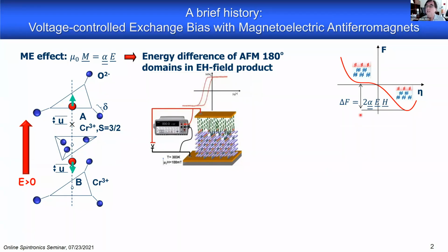Another important point I have not much time to talk about, but it's actually quite important for everything I say here. So you see, I make a little bit of distinction between the bulk of the material and this pink part here on top. It is not that at this point we have deposited any other material on top of the chromia. It simply indicates that the surface of this single domain crystal is special. It carries a magnetic moment.